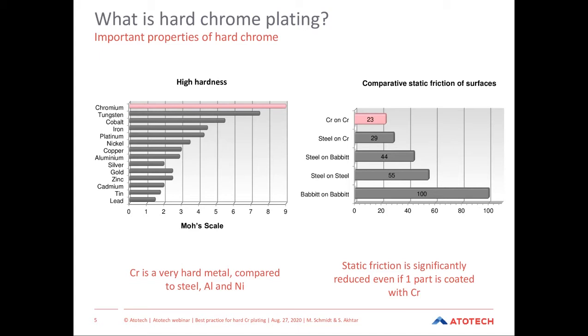The most important properties to consider, and the main reason why we try and plate hard chrome deposits, is that number one is usually the hardness, which imparts high resistance to wear, which is of course very important in terms of prolonging the life of the components. And secondly, hard chrome deposits provide a good coefficient of friction. This means the sliding properties of the deposit, which make it possible for the coating to be used in extreme environments with reciprocating dynamic movement.